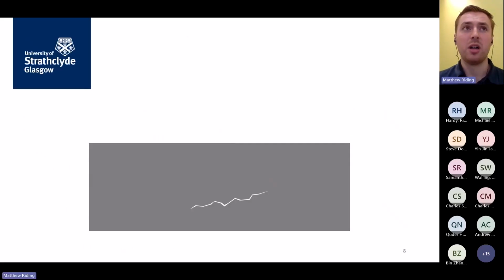So this brings me on to introducing the idea of laser ultrasonic inspection. When you use laser ultrasound, you can induce an ultrasonic pulse through a short pulsed laser that rapidly heats the surface of a sample. The rapid heating generates rapid expansion of the near surface material, and that expansion is accompanied by the emission of acoustic waves downwards into the bulk of the sample. These propagate and reflect off acoustic discontinuities such as cracks.